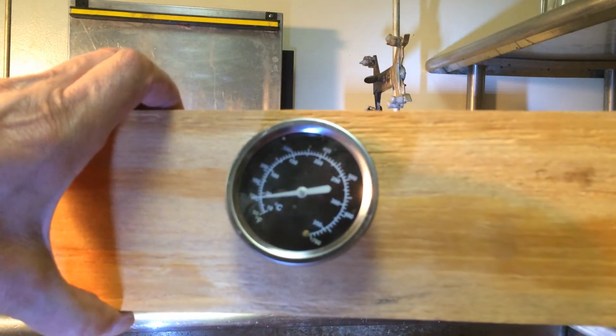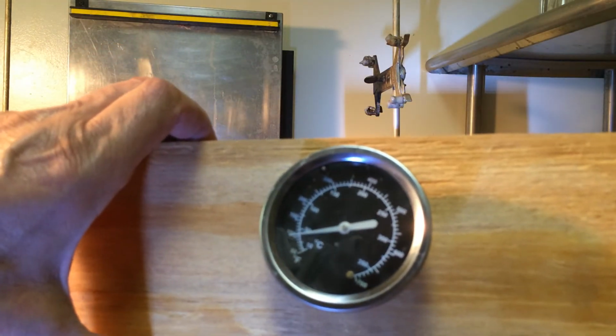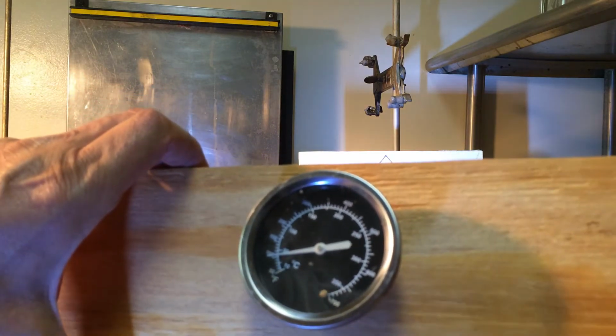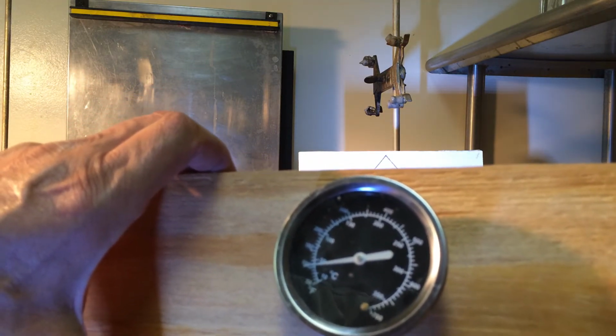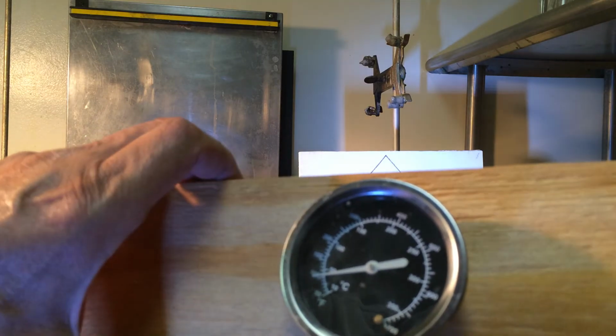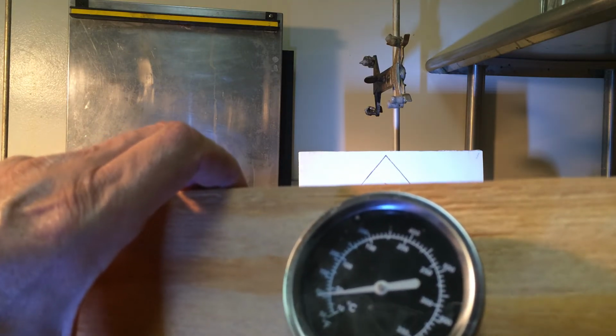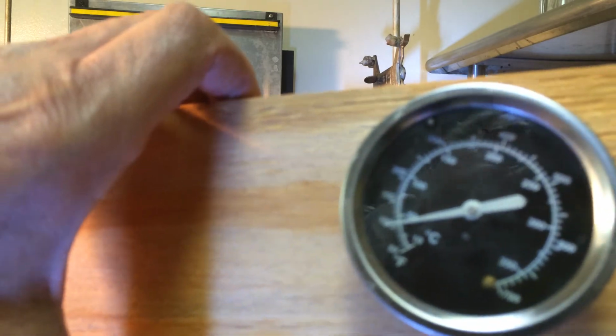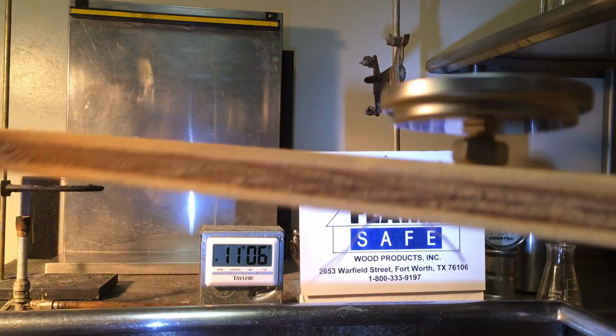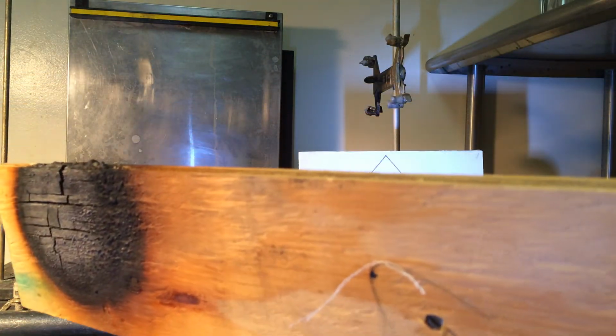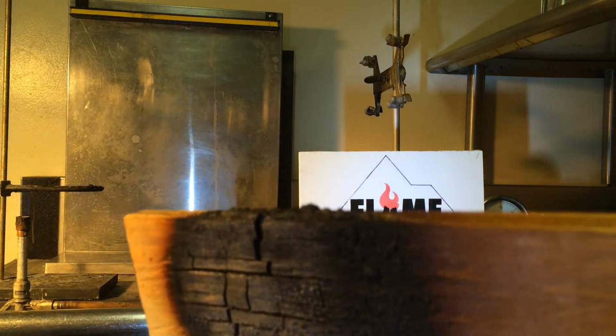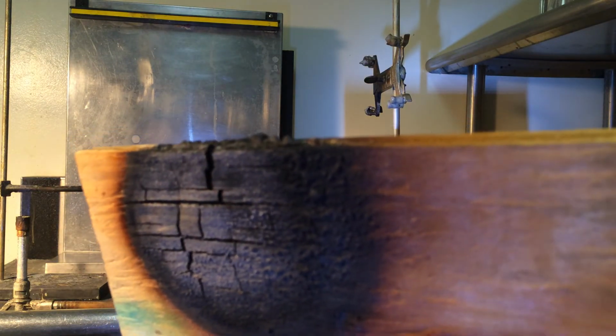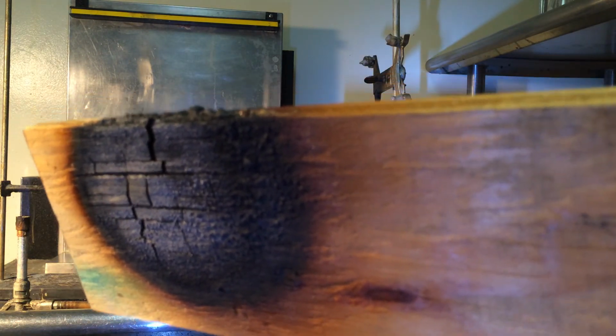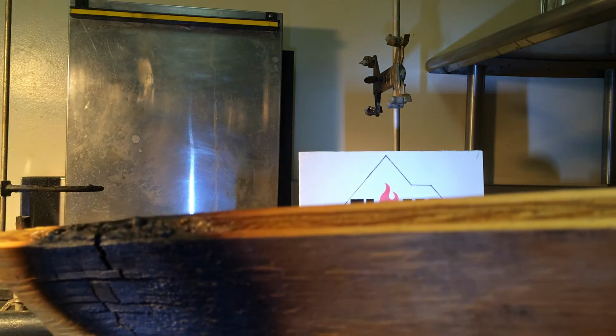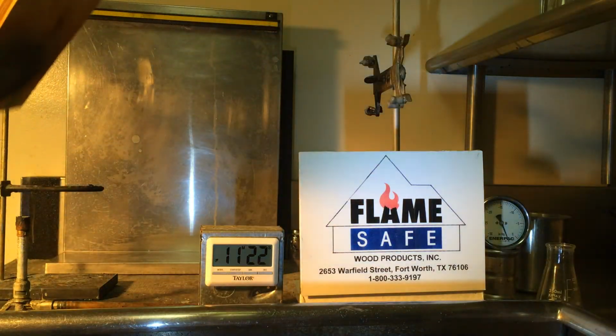As you can see from the thermometer, the specimen 8 inches away from the actual burning contact has not reached 100 degrees. And there is no after flaming. FlameSafe XT is the product of choice.